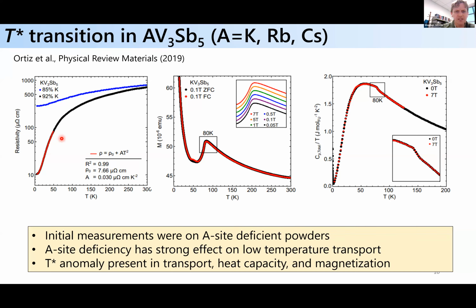But then if you look at magnetization, you can see as you cool down, there's an anomaly in magnetization where you see a dip. So as you cool down, the magnetization falls down. And there's a phase transition that you can also resolve in heat capacity around 80 Kelvin for the potassium system. It turns out this phase transition is present across the series, and it varies from about 80 Kelvin in the potassium system to about 94 Kelvin in the cesium system to about 110 Kelvin in the rubidium system. Okay, so it's a universal feature across the series.